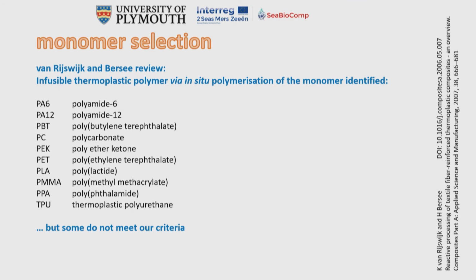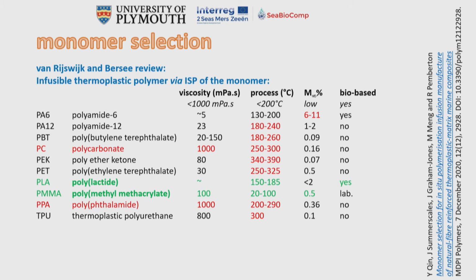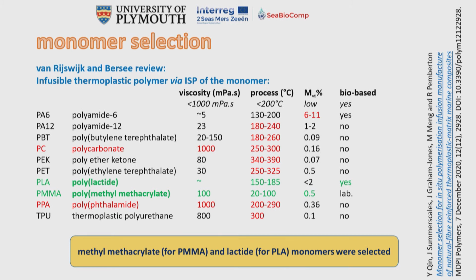We looked at the paper by Van Rijswijk and Bersee, who suggested there's a whole variety of polymers that we might use, but some of them don't meet the criteria we're aiming for. So the reds here process too hot. Some of them have got too high a viscosity. Reds in column 4 process too hot. In column 5, we end up with a very limited number of possibilities because of the moisture uptake. And then, is it bio-based or not? Well, we end up with polylactide, but it's got a high process temperature, or methyl methacrylate.